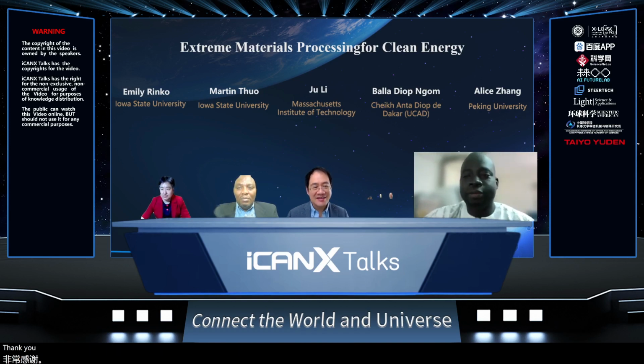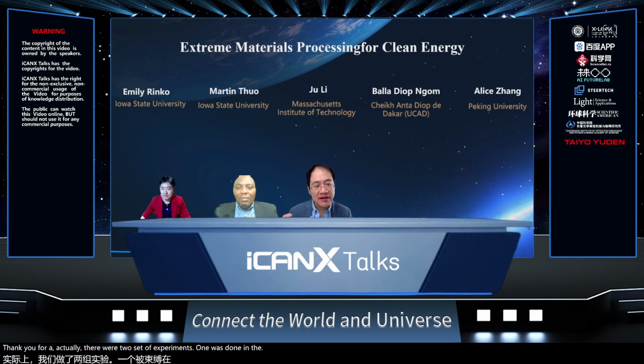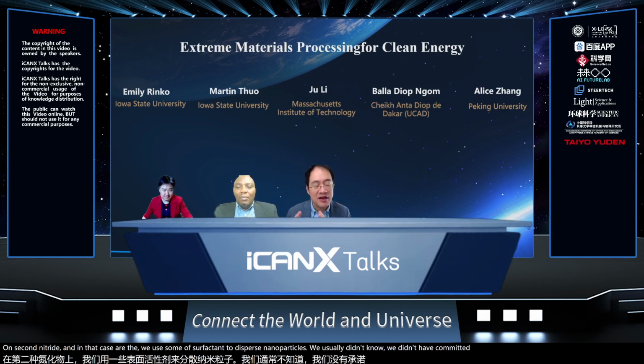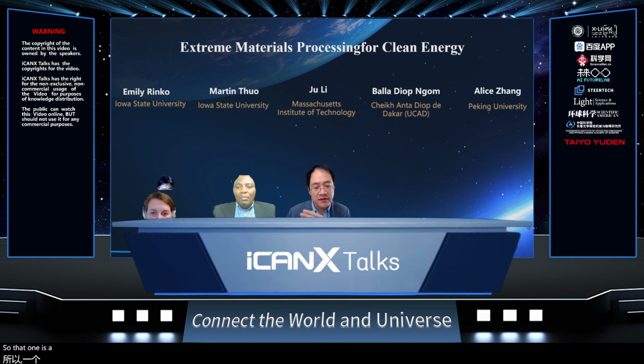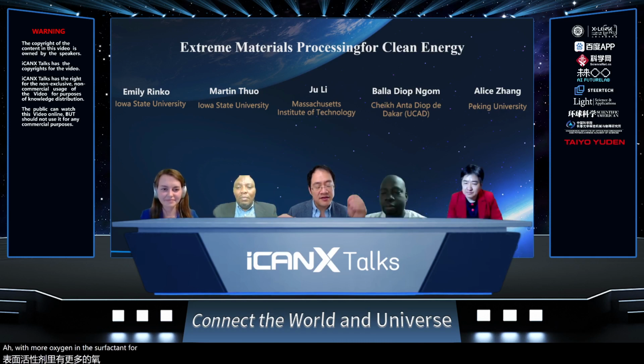Thank you, Bala. So actually, there were two sets of experiments. One was done in the in situ transmission electron microscope, and that was the palladium nanoparticle on silicon nitride. In that case, we used some surfactant to disperse nanoparticles. Initially, we were not aware of this. That is a hydrocarbon with no oxygen in the surfactant. So we had to have atmospheric oxygen and heating to 300 degrees, and then we saw the palladium start to move.